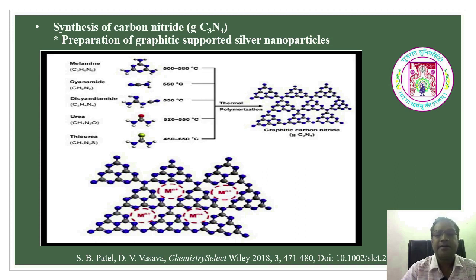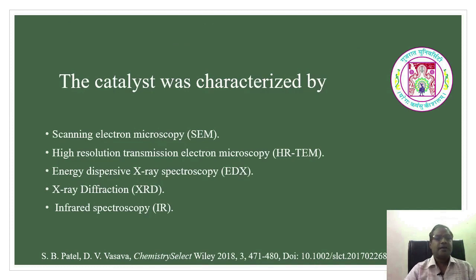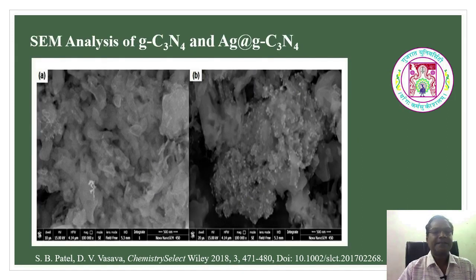Graphitic carbon nitride is synthesized by the reported method, and later on graphitic supported silver nanoparticles were synthesized. The synthesized graphitic carbon nitride Ag nanoparticles, that is the catalyst that we have utilized, was characterized by SEM analysis, HRTEM analysis, EDX, XRD and IR. So any nanocatalyst can be characterized by these techniques. Here in this work we have confirmed the catalyst by these techniques.